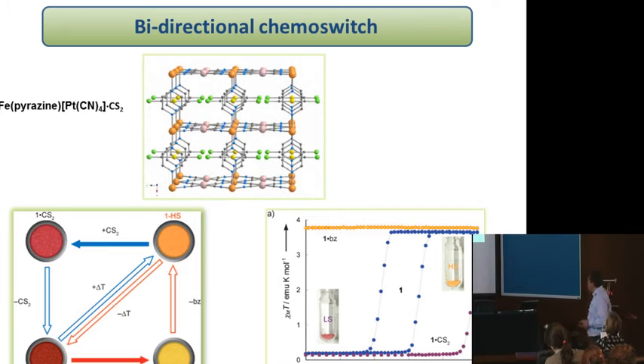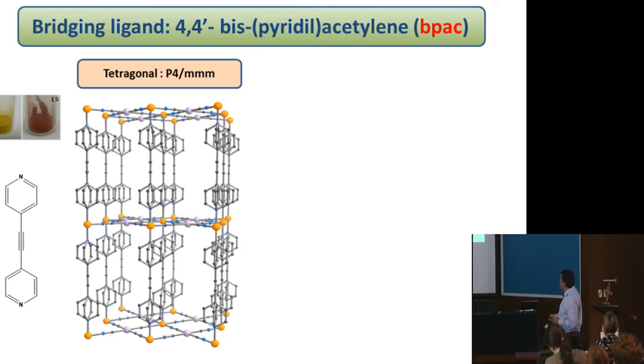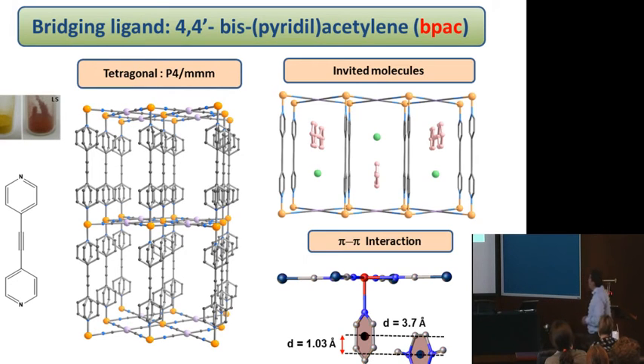Okay, so in the group we have developed this chemistry, and for example we have used these BPAC molecules, which is a longer and more rigid ligand compared to the pyrazine. And so we have obtained similar organization, so we always have these three-dimensional systems. What is interesting here is that the volume of the pores is 48%, which is twice the volume for the pyrazine derivatives. So, like this, we can increase both the cooperativity, but also the porosity in these three-dimensional systems.